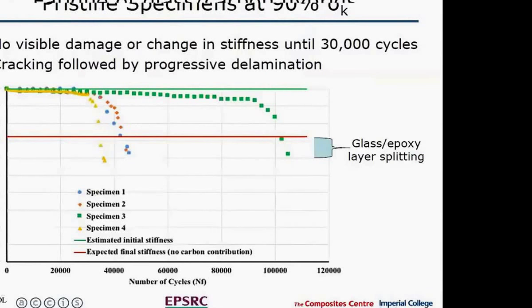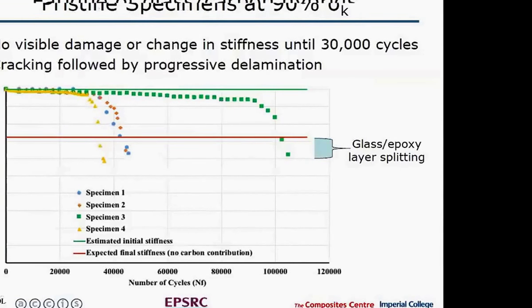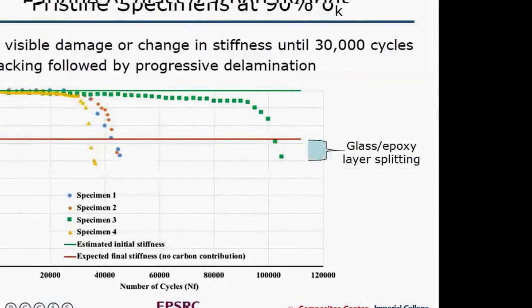Therefore, under fatigue loading, we get some fragmentation forming, and then delamination occurring from those. Therefore, we do see a reduction in stiffness. This red line shows where we'd expect to get to if we lose the contribution of carbon. And you can see it's actually gone a bit below there because there's been some splitting and some glass failure as well, so it's come a little bit below that line. But the important thing is that even at 90%, we get up to 30,000 cycles before we see any damage.